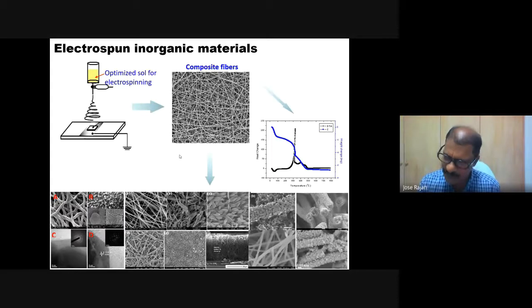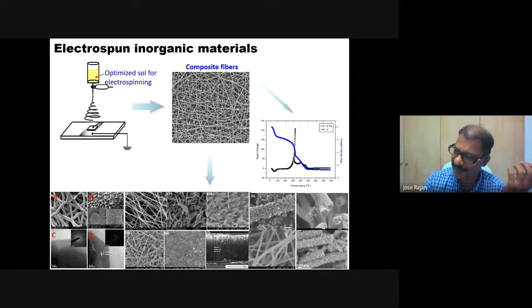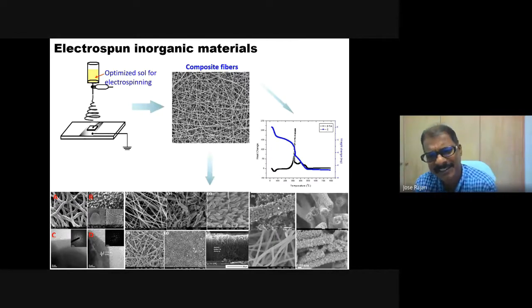The way it is done is, by conventional electrospinning, you get a polymeric mat. And if this polymeric solution contains the metal precursors for forming this inorganic material, then by appropriate heat treatment, take a DSC and TGA of this polymeric fiber and heat it at the required temperature where we find that some crystals are nucleating, you would get a crystal in a fiber, or you can tailor them to any shape you want. In our laboratory, we have developed numerous types of these electrospun inorganic nanomaterials in diverse shapes like fibers and cuboidal microcrystals and so on. And we have studied their properties in depth for two applications.